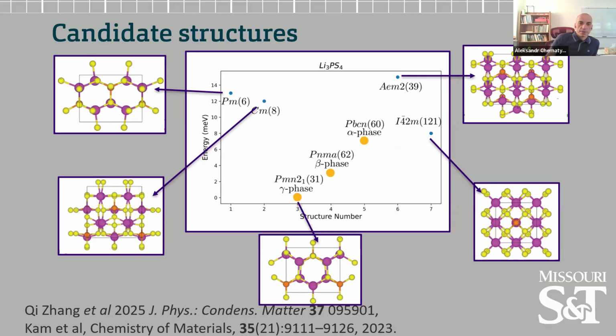Let me talk a little bit about agreement with the experiment here, because as I mentioned, gamma phase is the known ground state of the system. The phase which is most interesting for the application is the alpha phase. And as you could notice, we found neither the alpha nor the beta phase. The reason we didn't is because both of those phases feature disorder. In both of those phases, we have some degree of vacancies, which are randomly distributed throughout the system.